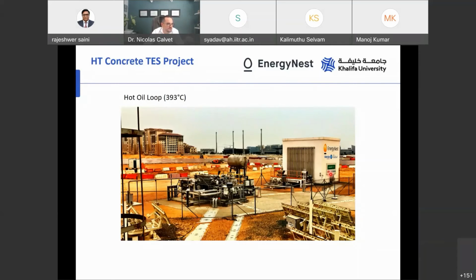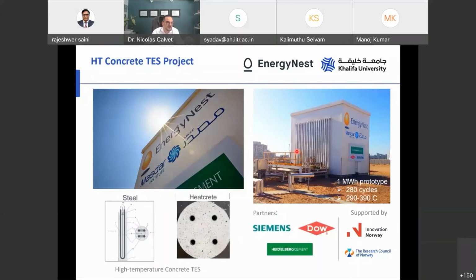So here the storage pilot, basically we have concrete columns, so 5-meter high columns. They are vertical in this pilot, but in the commercial, now they are horizontal. Doesn't change much. You have a U-shape, double U-shape heat exchanger embedded inside the concrete column. So the hot oil is entering here and exiting here, and entering here, exiting here, and that's how we charge the storage system. So we have done 280 cycles without any degradation of performance.